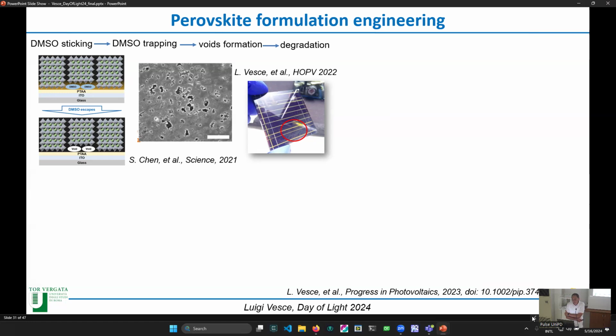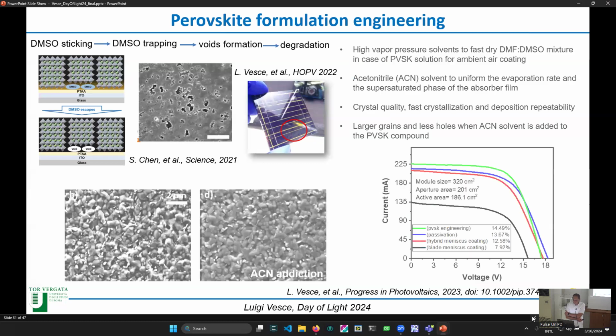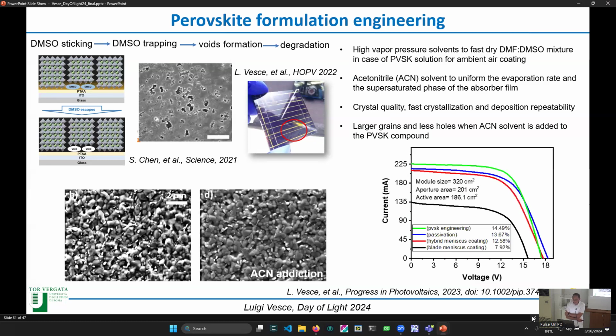These voids are the starting point of the degradation of the system, and so we decided to use some high vapor pressure solvent in order to fast dry the DMSO solvent. And so we use this acetonitrile solvent in order to have a uniform evaporation rate. We can also notice that we improved the deposition repeatability of the layer.